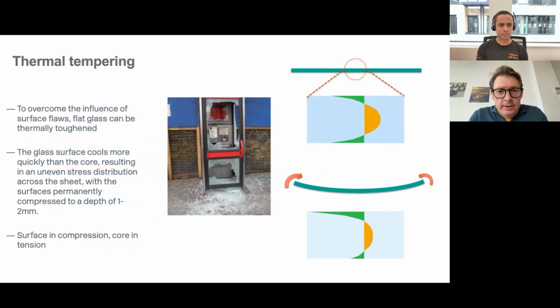But as I'm sure you're aware, tempered glass, because it's got so much strain in the material, releases all that energy when it breaks. If we look at a beam in the top right-hand corner, we can see that same stress profile as we had on the previous slide. But as we're bending that beam, those profiles change. Once a crack penetrates through the compressive zone into the tensile zone, all that energy is released, and we get these broken cuboids of glass. What that means is that the glass is failing safely, and historically, in inverted commas, that's been classified as a safety glass because it fails safely.